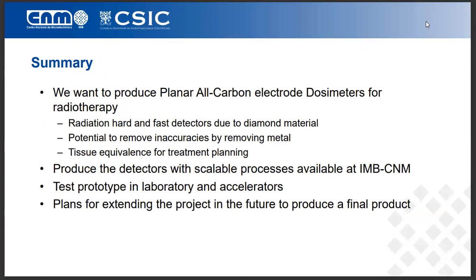This is the summary. We want to produce these planar all-carbon electrode dosimeters for radiotherapy, because diamond is a radiation hard material and a fast detector. There's potential to remove inaccuracies by removing the metal layer, and replacing the metal with graphite makes it more efficient. So we want to produce those devices with a scalable process available here, and then we test the prototypes in the laboratory and at accelerators. And of course, if all goes well, we can even extend the project to produce a final product. And that's everything from my side. Thank you.